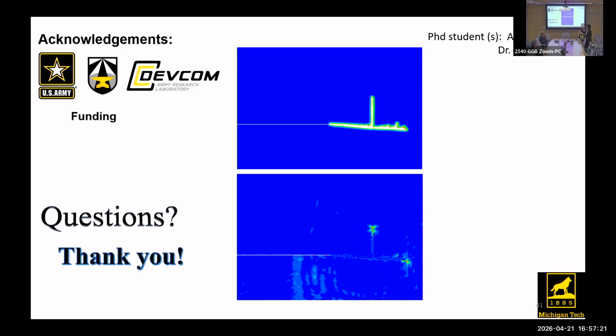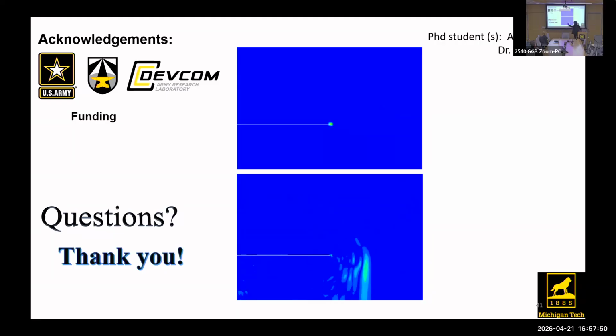So the model does not have anything to precisely determine where the branching will happen. The branching here is happening as you have enough energy to create another crack. If you see this phenomenon here, the bottom one is showing how the stress wave is propagating, and that one is the crack. So when the wave comes, that is when you hit, and the crack starts horizontally. Okay, so you see that?